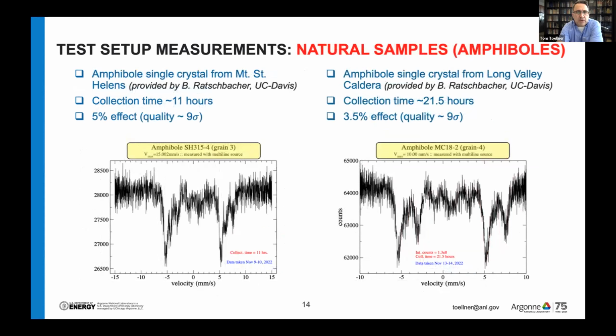We also measured some unenriched samples. These are amphibole single crystals provided by B. Ratschbacher. The one on the left is from an amphibole single crystal from Mount St. Helens. These samples have very little iron in them, and of course, they're unenriched. So the collection times are significantly longer. We measured this for 11 hours, and you see the data quality isn't as good as the spectra on the previous slide. But this is the kind of spectrum you can expect in about 11 hours. And obviously, you would want to collect on this sample for many hours.